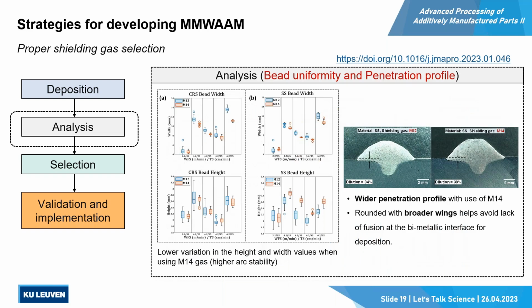Next to the arc stability, we also check the bead geometry. For example, the uniformity of the bead height and width, and the variation of the dimensions, and also the cross-section of the beads to check the penetration. You can see from gas A to gas B, the penetration has been increased, which can guarantee a good bonding between the material and the substrate, and also the bonding between each layer. This was for the arc stability and the shielding gas selection for two materials.